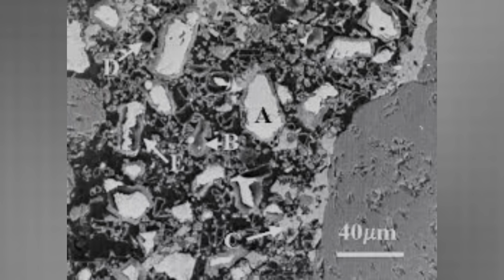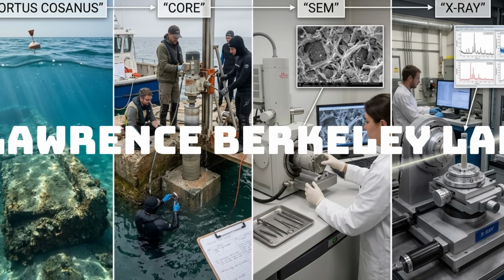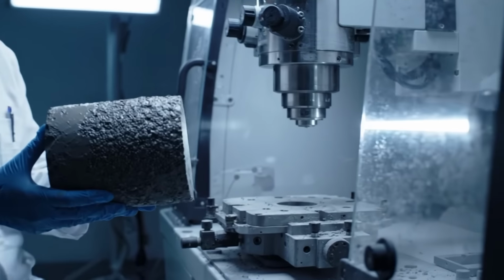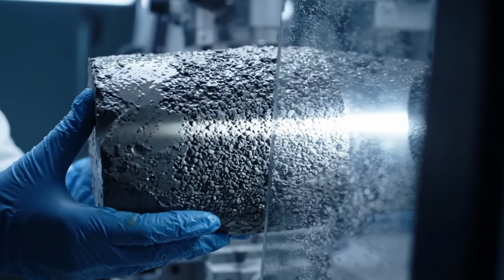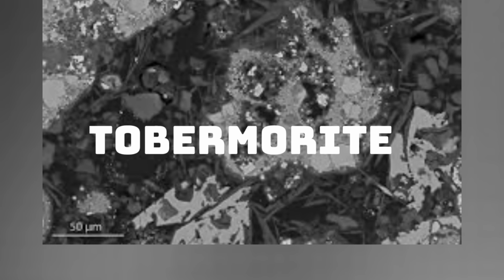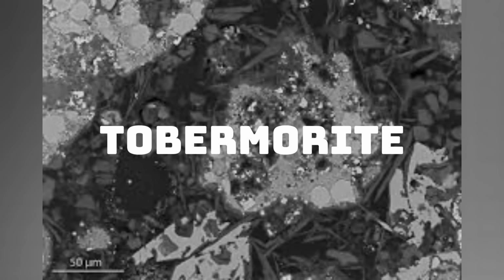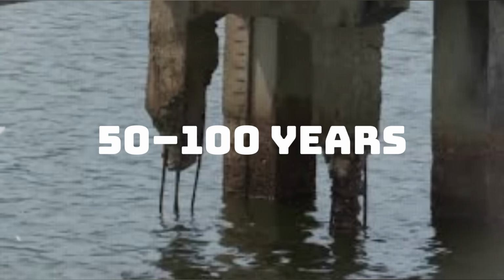They ran those cores through electron microscopes and synchrotron X-ray beams at Lawrence Berkeley National Laboratory. What they found should not have been possible. Inside the matrix, an unusual mineral called Aluminous Tobermorite was still forming, still growing, still interlocking, plate by microscopic plate, after 20 centuries underwater. Modern marine concrete is engineered for a service life of 50 to 100 years.